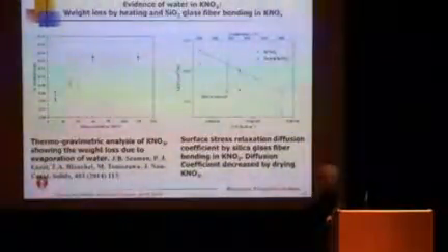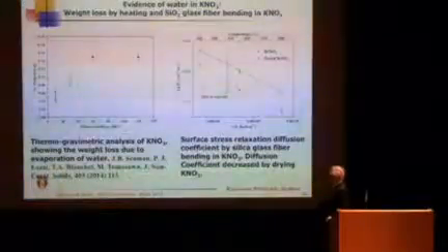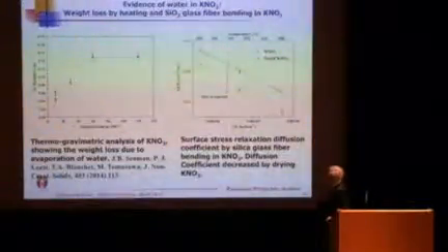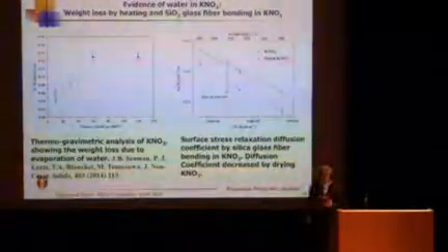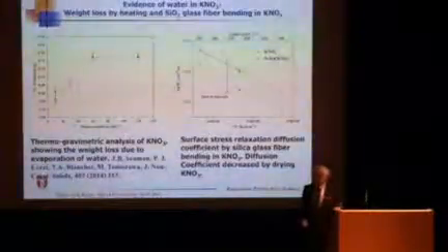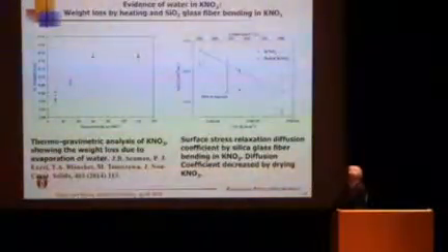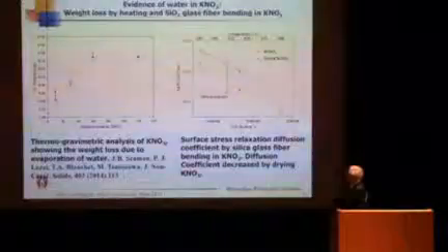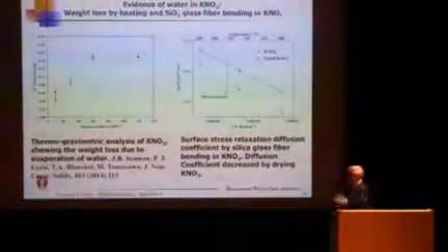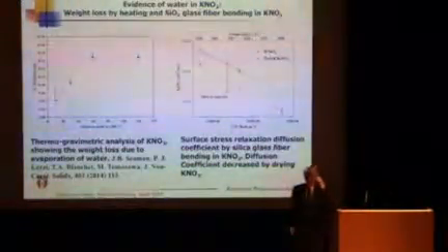So we kept the KNO3 in solid powder and then measured the weight loss. And sure enough, weight loss happens. So I believe water is evaporating from this powder. And using this, before and after the heating, we did this fiber bending test I mentioned.